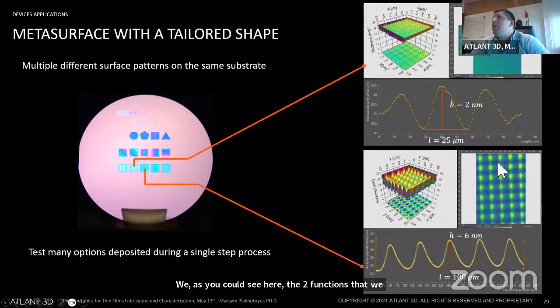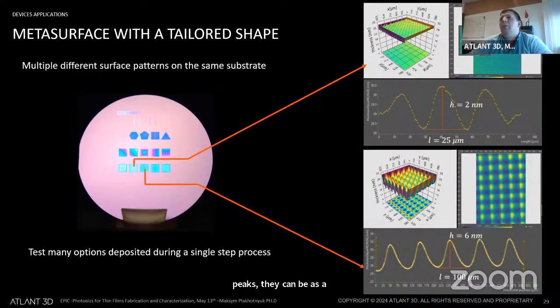Another very interesting test that we did. So meta surface and the surface modulation, basically. As you could see here, there are two functions that we implemented. One has this type of shapes. I don't know how to call them. Another was with just peaks. They can be even as well as uneven. And it really depends on the geometries. And again, this is in automatic mode that we did. We did these measurements with imaging ellipsometry just to confirm that we obtained what we expected.